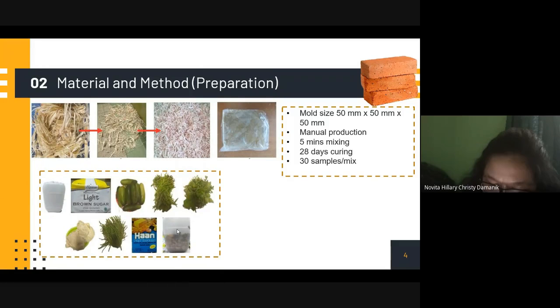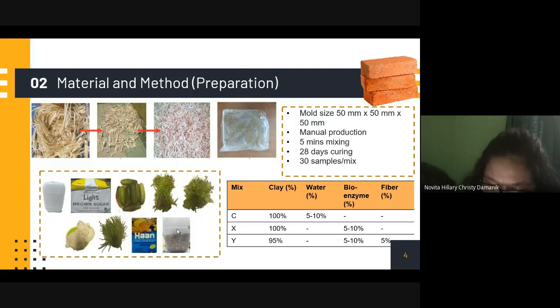By using a mold of 50 by 50 by 50 millimeters to make the samples for the next testing in compressive strength. This experiment is manually produced without the help of a machine to test the brick. There are 3 different mixtures. The first one is the control specimen without additives. The second one is X, which contains only fermented vegetables with a percentage of 5 to 10%. And the last one is Y samples, which contains both sugarcane short fiber and the extraction of fermented vegetables.